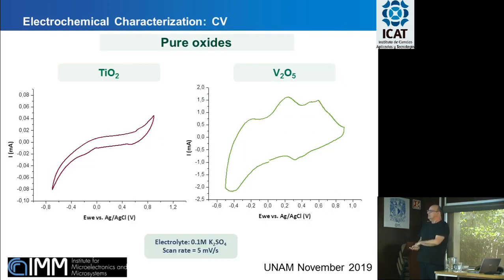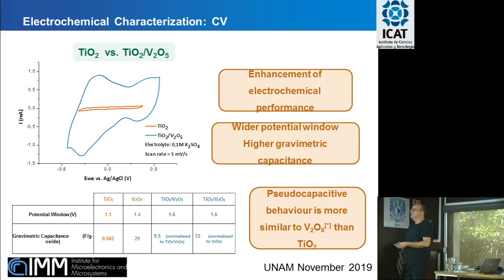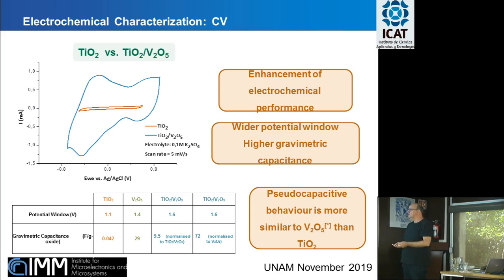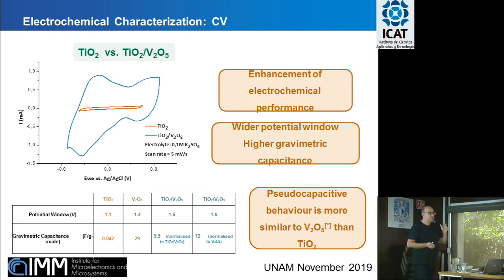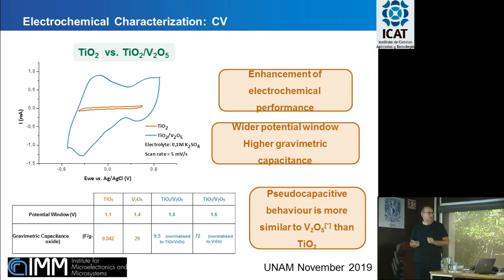These are the voltammetry curves of the pure materials, titanium and vanadium, and when we compare our titanium vanadium material with the pure titanium, we see that there is an enormous improvement of the properties. We have a wider potential window and higher gravimetric capacitance, which means that this small addition of vanadium onto the surface was capable of increasing enormously the capacitance of the material when working in the same condition of pure titanium.